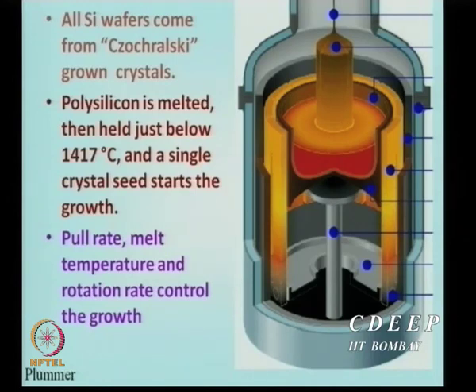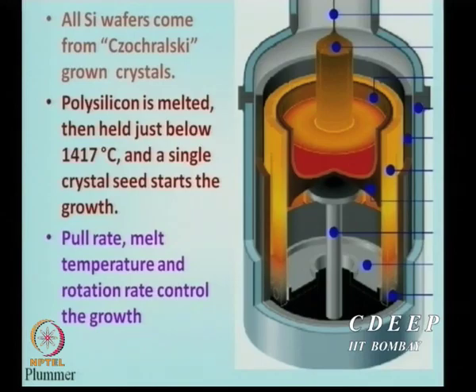So oxygen is anyway added by you whether you like it or not. Boron itself can be added as a powder material, but it is very hygroscopic — it picks up humidity very fast and becomes jelly. So we normally use boric acid powder which is available in the market. You add this to the melt, it dissolves, and when you start pulling the crystal, some part of the impurities also go along from the melt to the surface and then into the crystal rod. This is how impurities are added in the case of CZ.